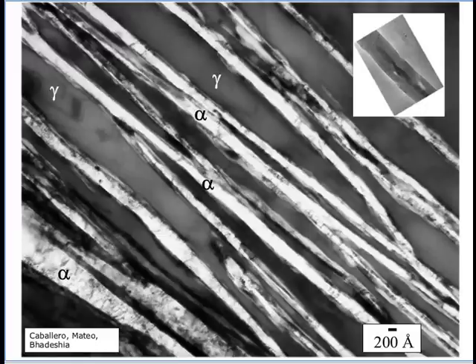These crystals are 20 to 40 nanometers in thickness, and you can produce large quantities of steel, large in all dimensions, having this crystal structure. This is the world's first bulk nanocrystalline material, and the austenite has the job of adding a work hardening capacity. So this steel is strong, about 2.5 gigapascals in strength. It is tough, about 45 megapascal root meters, and it has ductility.